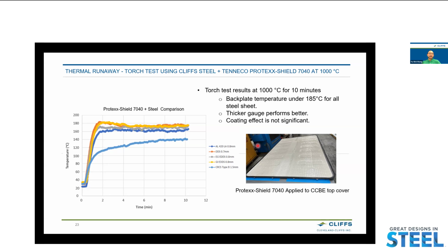Also, from the chart, you can see that the gauge has a positive impact. With a thicker gauge, the better the performance. However, the coating does not seem to have a significant impact on the result. As I mentioned again, Tenneco has performed a series of extensive tests. So if anyone's interested, we can provide the details.